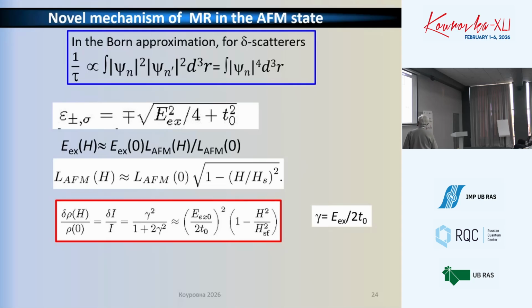It roughly can be approximated as the exchange splitting in zero field times the ratio of the antiferromagnetic vector versus magnetic field, normalized by its zero field value. The antiferromagnetic vector is proportional to the square root of 1 minus h squared. And as a result, we obtain the correction to the resistivity, the magnetic resistance, negative and parabolic, and its magnitude is dependent on the ratio of the exchange splitting in zero field and t-naught, the hopping overlapping in the cross direction.